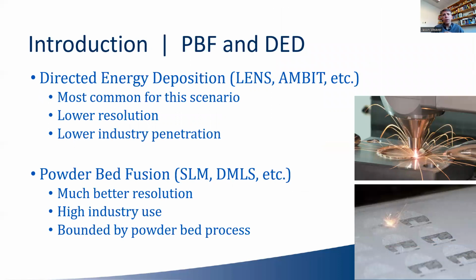There are a few different ways of additive manufacturing of metals. Two of the main ones here are DED, directed energy deposition, and powder bed fusion. It comes under a lot of different names, SLM, DMLS, laser fusing. There's a lot of different variations. For the scenario that I was talking about, adding additional material to an existing part, we typically use directed energy deposition. You can see in the top picture, this is where we're spraying a powdered metal typically, and then at the same time creating a melt pool by shining the laser on the material as it's fusing to the substrate, the existing part.